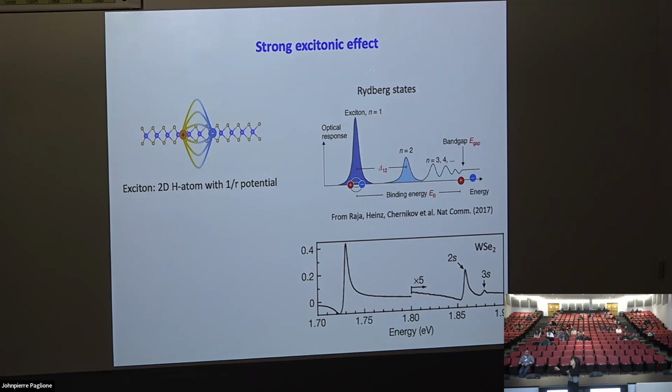You can see the fundamental exciton state and those highly excited states. And then the continuum has a very subtle signature. It's hard to tell. But from the separation between 1s and 2s, you can roughly estimate the exciton binding energy.